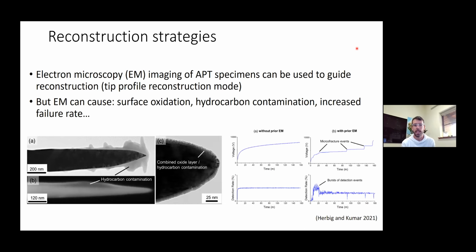However, we know that electron microscopy can cause some issues. Surface oxidation and hydrocarbon contamination are two important ones, and these basically increase our chance of failure, so increases our rate of failure.